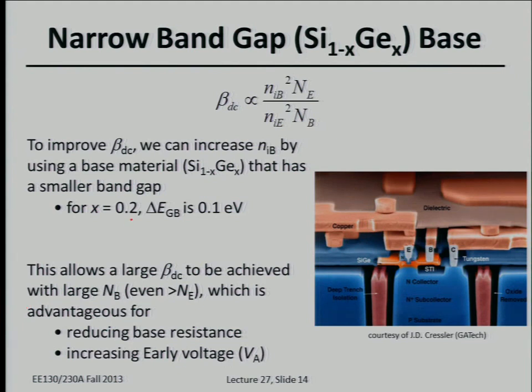For example, if the mole fraction, or the concentration, of germanium is 20%, then the band gap is smaller by about 0.1 electron volts. Let's say, for example, delta Eg is equal to 0.12 electron volts. I think that's about one order of magnitude. Bottom line is, if you have a smaller band gap in the base, then you have higher Ni squared in the base, and that enhances your current gain.